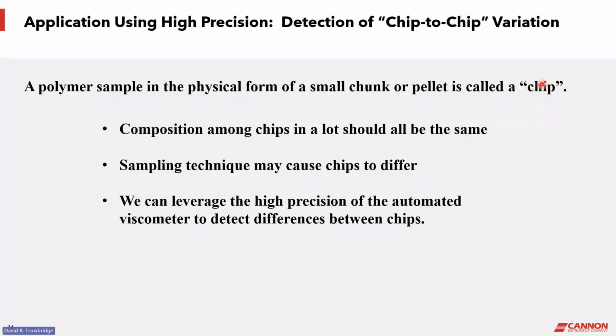Now, there's also an opportunity I want to take here to show the high precision applied to the analysis of chip-to-chip variation. A chip is simply a term for a pellet or a chunk of a plastic sample. And the idea is that these plastic samples are not different from one another. When you take them to analyze them, you're assuming that every chip you take from the lot is going to be the same as the next. But in fact, that sometimes isn't the case because the sampling technique isn't perfect, and there'll be possibility of variation between the chips. And sometimes you want to confirm that you have chips that are representative of the lot. And so this experiment was an effort to do that.